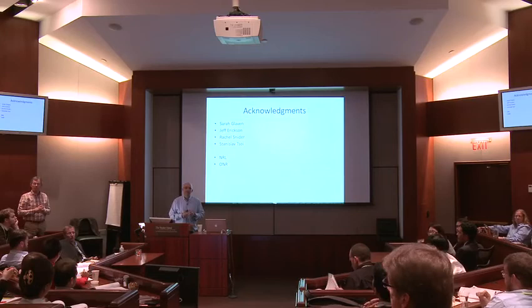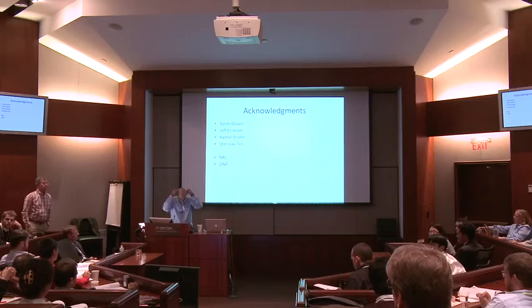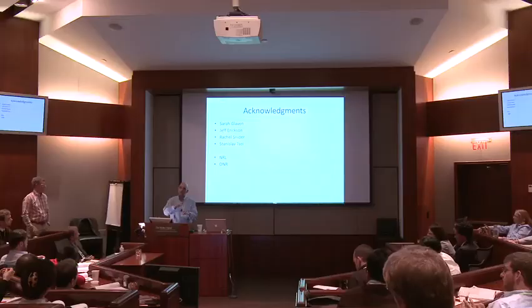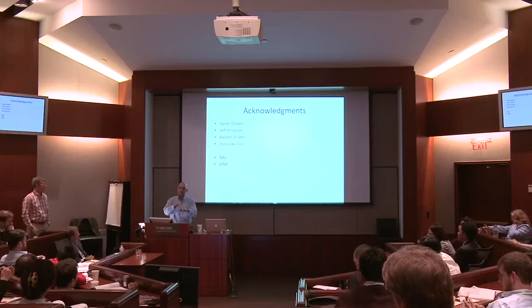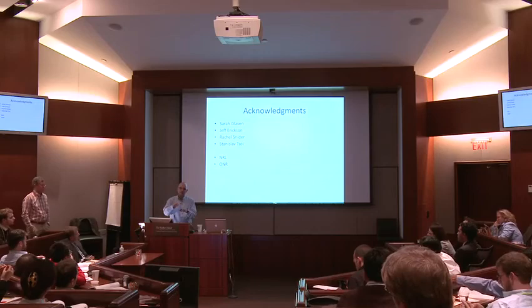So if you have a better ability, a higher driving force to pump the electrons through? Yeah, according to a mediator model, if you apply a more positive potential to the anode, the rate of the electron transfer reaction between the mediator and the electrode is what's the final step, right? And so once the electrode becomes positive of that, you don't get anything more thermodynamically. You can make it more and more positive. Once it's positive enough, the electrons flow through. It doesn't matter if you make it any more positive. So experimentally, most people observe that as you poise the anodes more and more positive, you don't get any increased biofilm thickness at all or any higher catalytic activity.